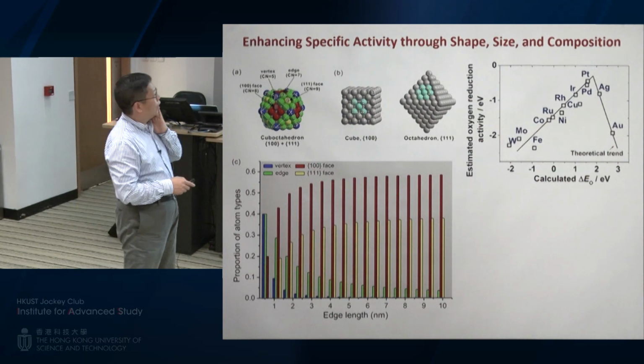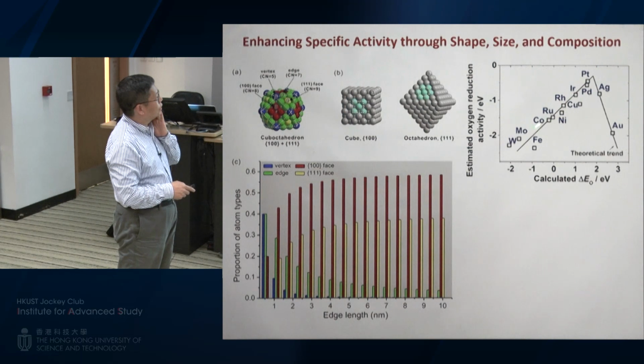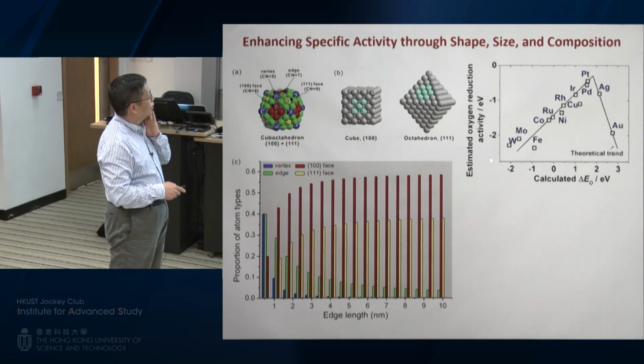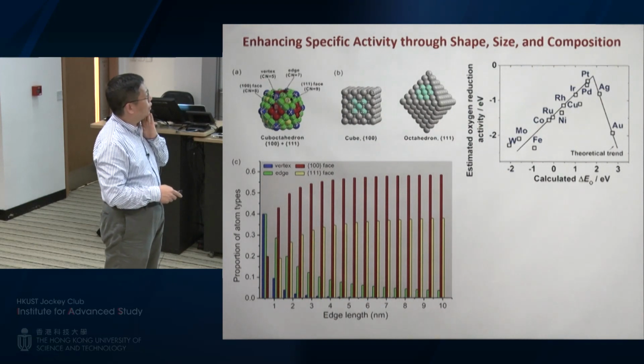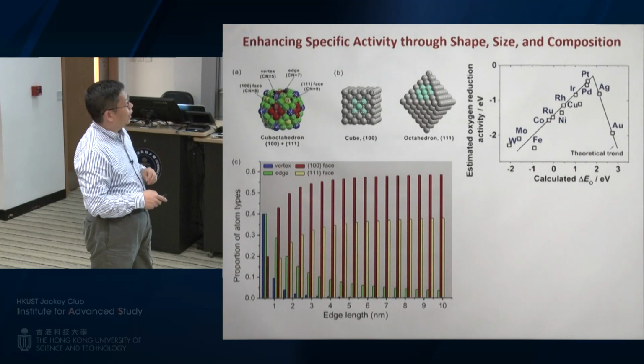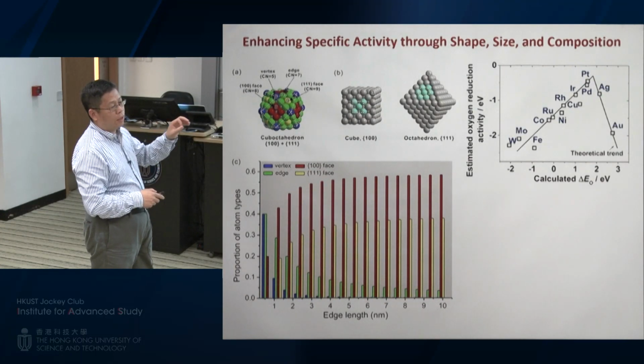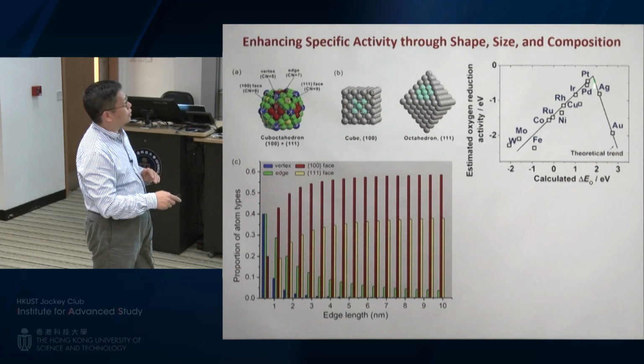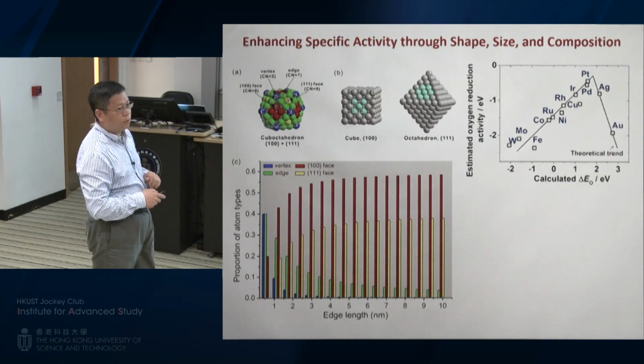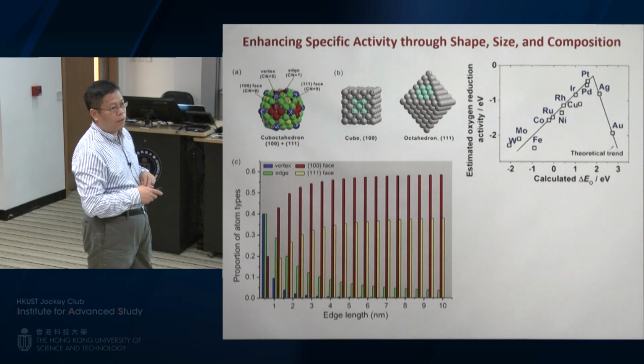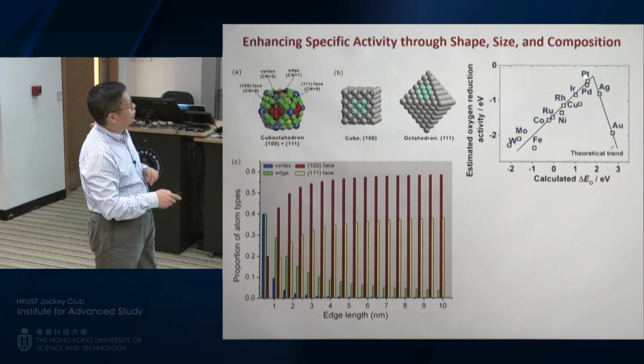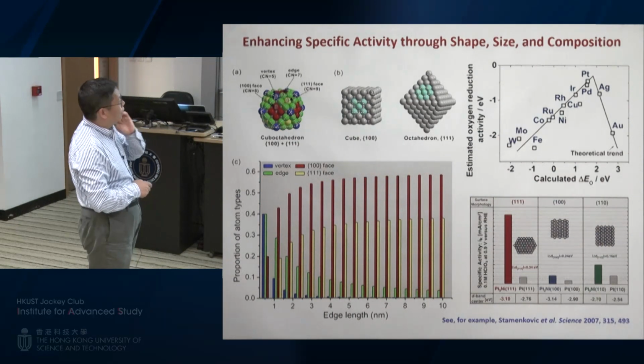And then about the composition, platinum turned out to be the best. If you think about this volcano plot, this is basically the activity as a function of the bonding energy for the oxygen species on the surface. And this is a well-known phenomenon for catalysis. The binding cannot be too strong or too weak. So it has to be optimized somewhere in the middle. That's why it's called a volcano plot. Platinum is sitting at the top over here. It turned out to be the best. And for silver and palladium, they may have something close to platinum, but unfortunately, in particular palladium, those metals are not so stable compared to platinum. They could be oxidized, for example. So that's why platinum stands out over there as the best choice for oxygen reduction.